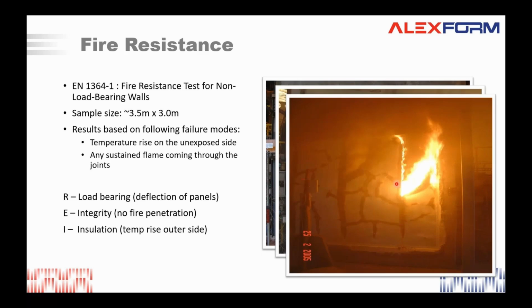It has to continue more than 10 seconds as a fire. Then they stop the test and it's the failure point. So this is the fire resistance test, the most famous one. And it will give you results like, for example, EI30, which will mean this panel withstands fire for 30 minutes without losing its thermal insulation and without letting the fire go through it.